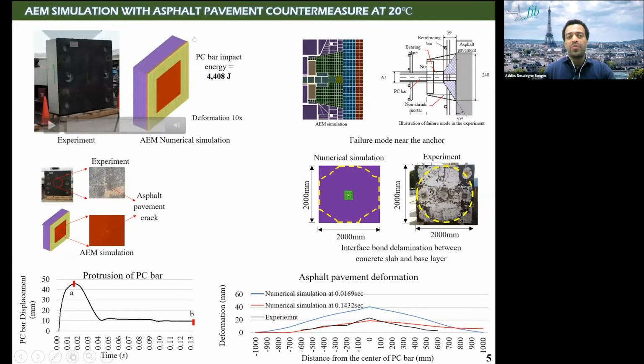Also, this one is a numerical simulation and experiment with the asphalt pavement countermeasure at 20 degrees centigrade. This experiment is conducted at 20 degrees centigrade, and this one is a simulation. So you can hear the sound when the bar is ruptured and impacting the asphalt pavement, but there is no major damage on the asphalt pavement. So the asphalt pavement countermeasure was effective in consuming all this impact energy from the PC bar. Similar results were also obtained using a numerical simulation.